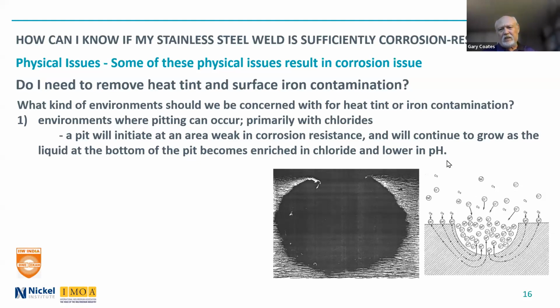And people say, well, what kind of ppm level of chloride should we be worried about? Well, we've seen it as low as maybe 10 or 20 parts per million, where if the chlorides can concentrate, usually through some sort of evaporation mechanism, that can cause the chlorides to rise to a much higher level. And so from a point of view of concern, you have to start thinking about it when you have 10, 20 parts per million. May not be a concern depending on the alloy until you get much higher, but you have to at least think about it and eliminate it if possible.